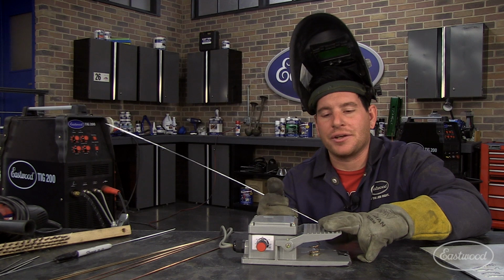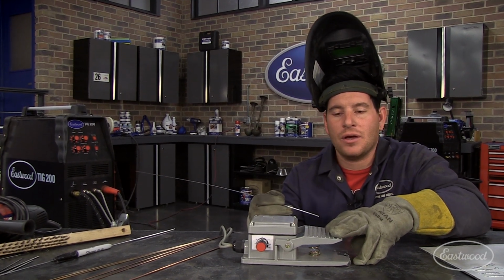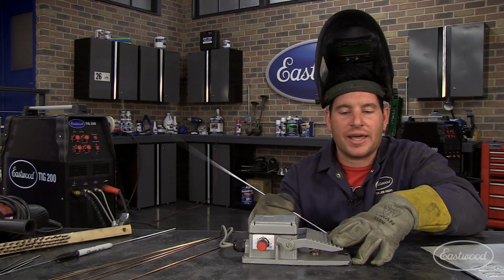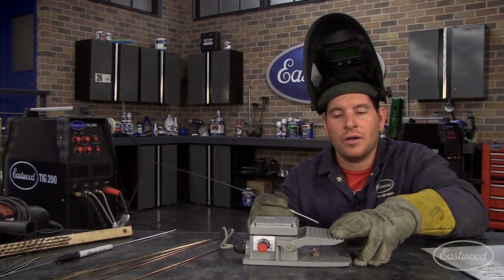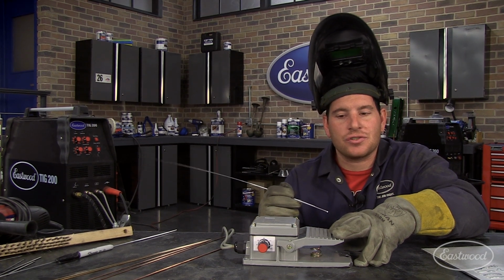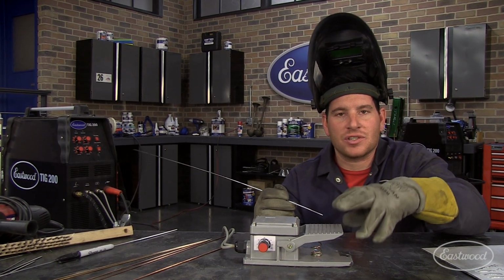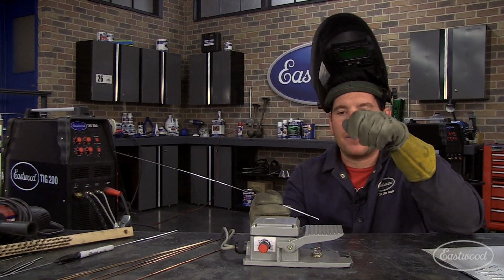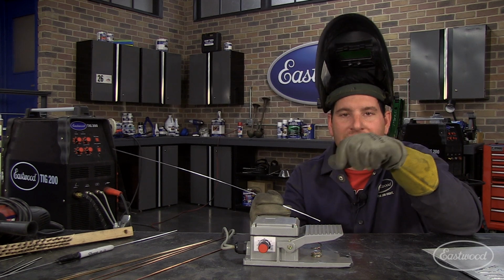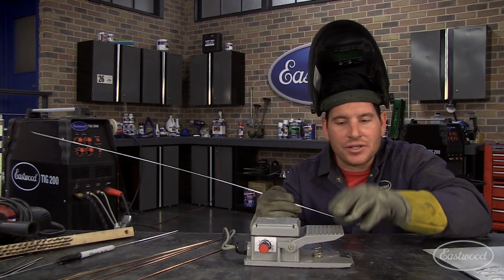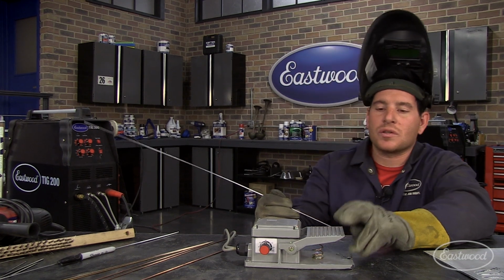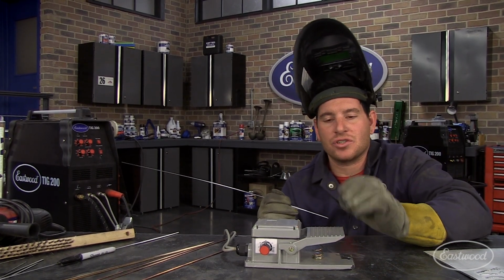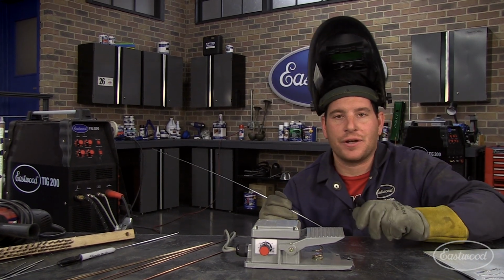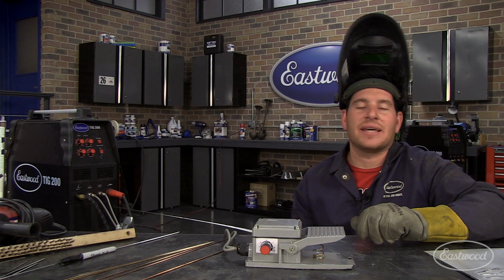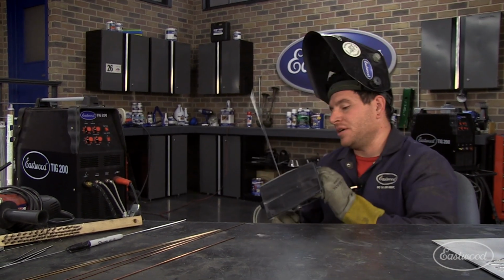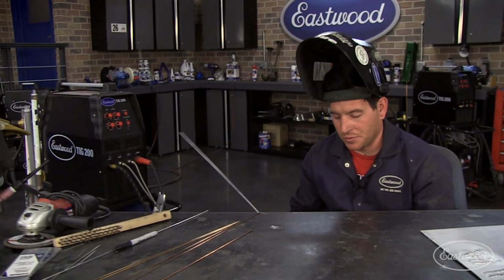So what you want to do is when you're getting near the end of a weld or near the end of a joint that you're welding, you want to let off the pedal real slow and just let the arc dance around and slowly let the metal get to the point where it solidifies. You can even move your torch around a little bit, put that last dab of material in, and then slowly start letting off your pedal. What that'll do is let the metal slowly solidify, and it'll avoid having those craters or cracks in that last dab. That's very, very important. That's something that a lot of people forget. Get yourself in that habit when you're welding.